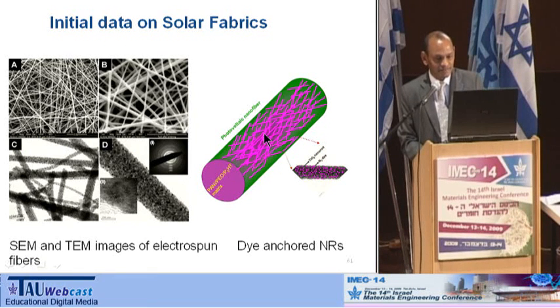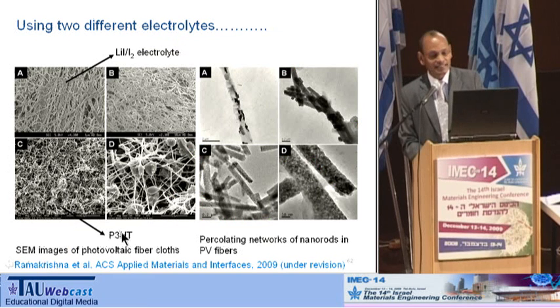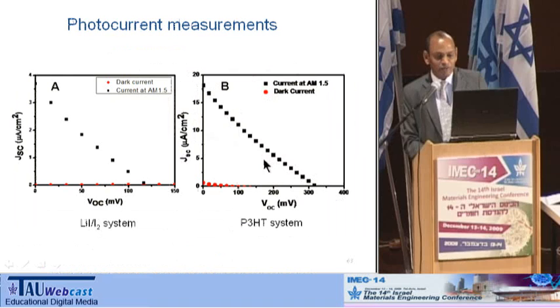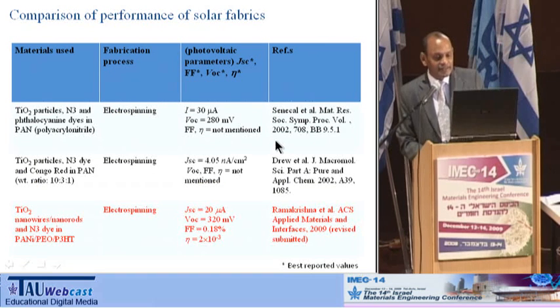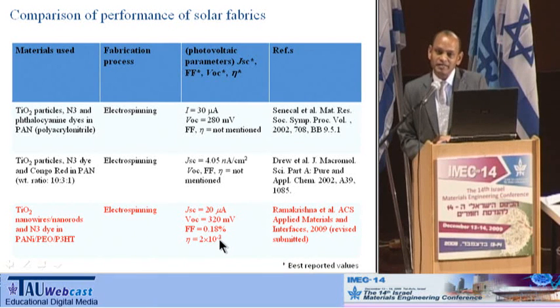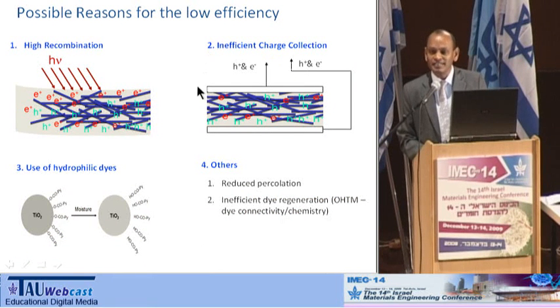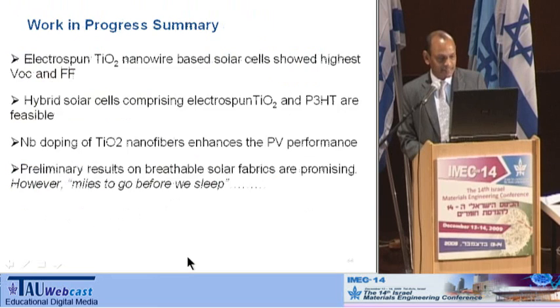These are the initial results, where you have the TiO2 nanorods coated with the N3 dye, which is one of the ruthenium dyes. And these are TEM examples of these fibers. You can make them with different electrolytes, a P3HT system, as well as lithium iodide systems. What I wanted to show you is the first proof of concept. That's the dark current, that's the light current, and you notice that there is an improvement. The efficiencies are not very high at this point, but it proves that such a concept would work. Now it's a question of optimizing this particular approach. We have issues in terms of recombination, charge collection, as well as the dyes. So we are in the process of optimizing these.